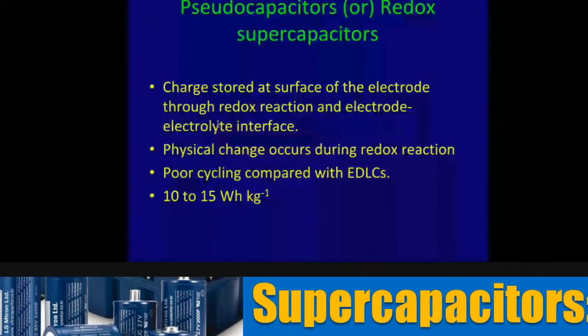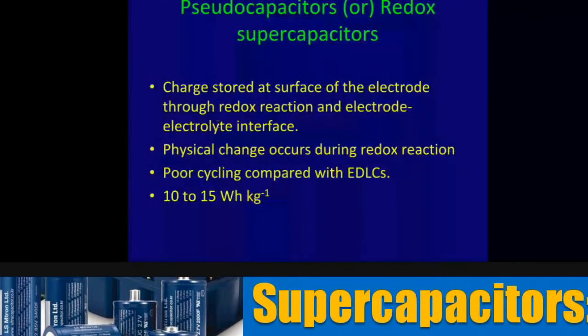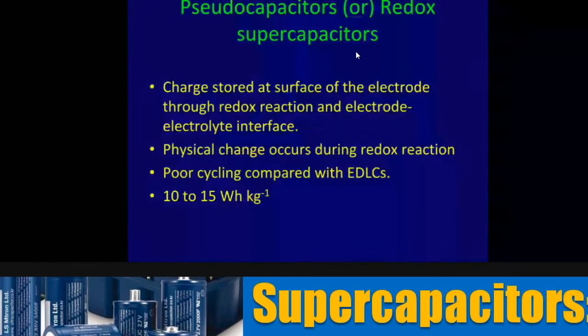Now we will move over to pseudo-capacitors. The pseudo-capacitors are the so-called reduction oxidation capacitors known as redox supercapacitors. Here the mechanism is entirely different. Though a part of the charge is stored at the surface of the electrode through the redox reaction, the interior of the material takes part in the redox process, and we have excellent capacity because we are able to use the inner sides of the electrode.